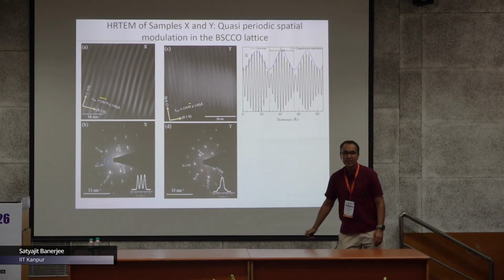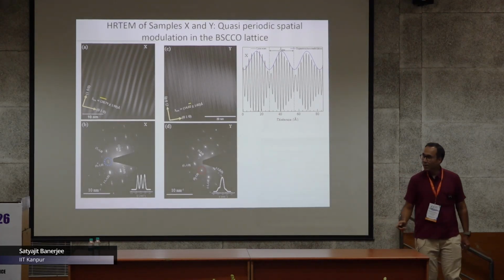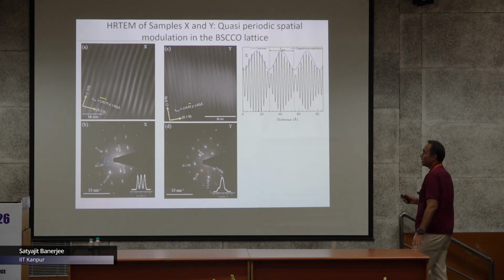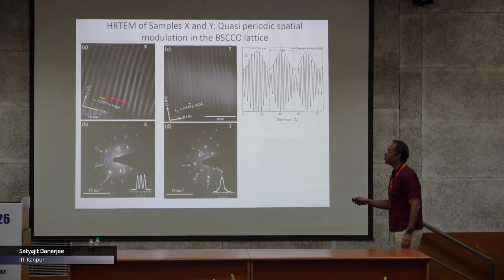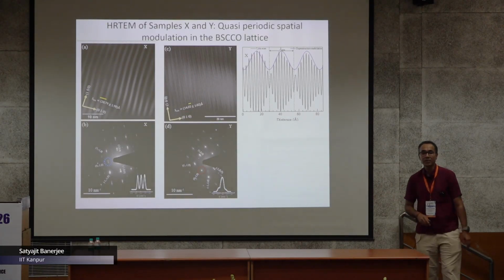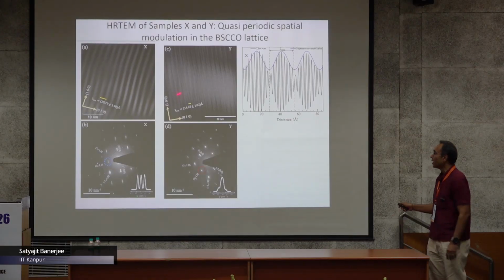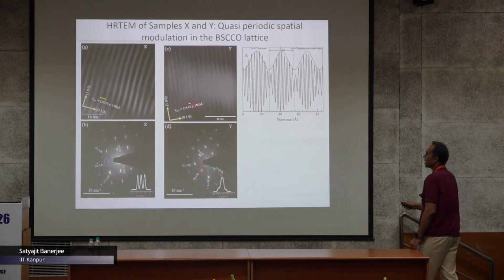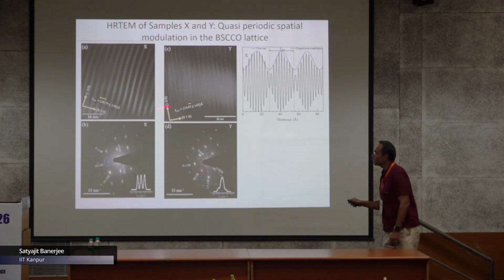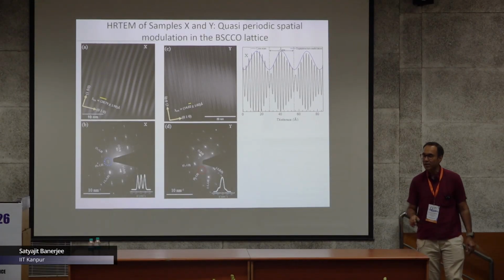Now if you do oxygen annealing in the system, under certain specific conditions, this periodicity is significantly destroyed—it's almost gone. You can make out faint periodic structures, but it becomes a highly quasi-periodic structure.